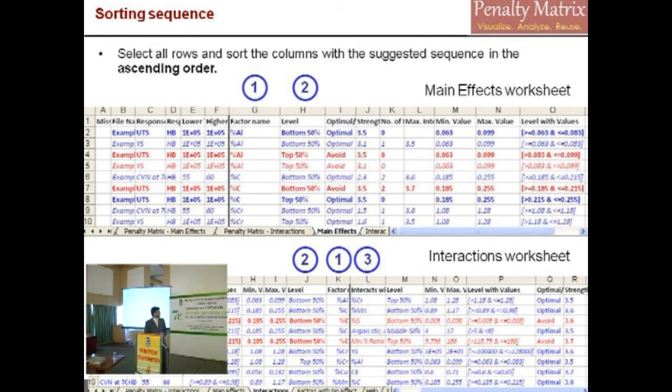But we've got a problem with carbon. Carbon bottom 50% is optimal for toughness, not very strongly, but it has two interactions and the strength of interaction is high. But carbon bottom 50% is bad for UTS. So you need high carbon to increase UTS. And then you have the actual range as well. So it is not just domain knowledge within the train, but actually the range which works for your foundry. But now there is a conflict with carbon.